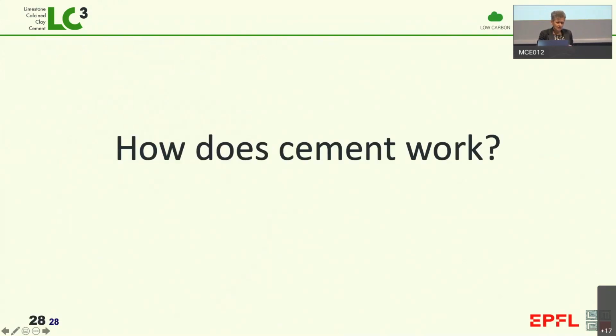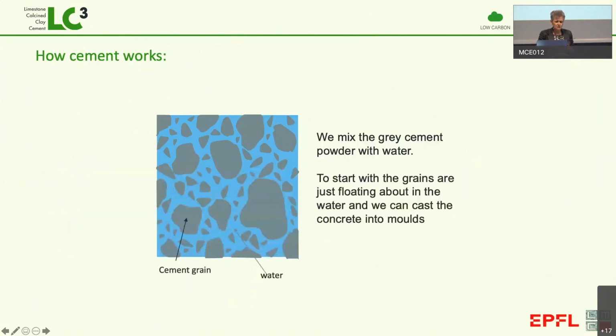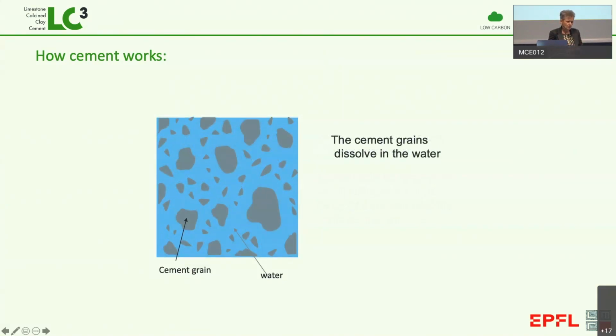And then we need to think about how does cement work? Well, it's really a very interesting process because we start with this material where we have these gray grains floating around in water, and that's what makes it nice and fluid. You can make it into all these different shapes. You can transport it onto site. And then what actually happens, those cement grains dissolve. So that's like when you put sugar in your coffee or you put salt in your cooking water, it dissolves. But unlike your salt or your sugar, that's not the end of the story.